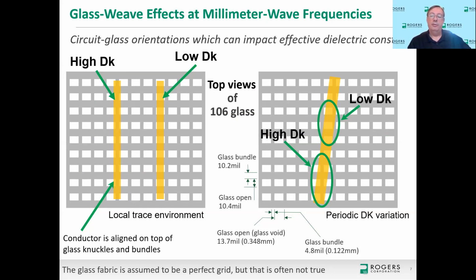Now to the right of that is the periodic DK variation, and personally from going through a lot of studies and experiments, I think this periodic DK variation is the real issue, and the local trace environment definitely can be an issue too. But I think most of the glass weave effect issues that I run into is probably related to the periodic DK variation. Unfortunately, it's very hard to do an experiment and verify this.